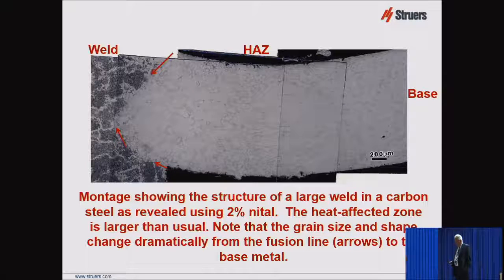But you can see here that this is the base metal. This is etched with Nital. And I had to stop etching because the weld metal was getting over-etched. But the original steel is not as well etched. But you can see this is the base metal. And here we're in the two-phase region, but the structure is not showing up very well. But you can see a little bit of hint of acicularity. And this steel was not aluminum killed.